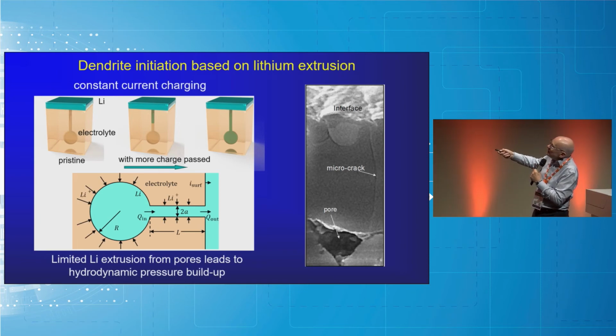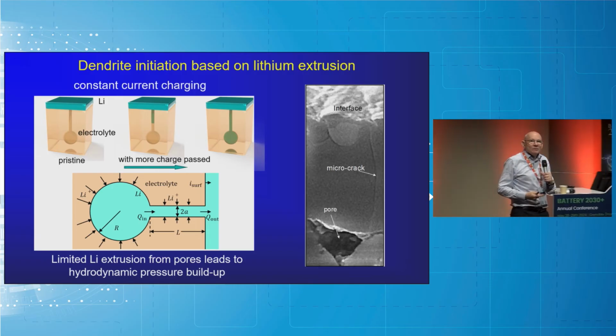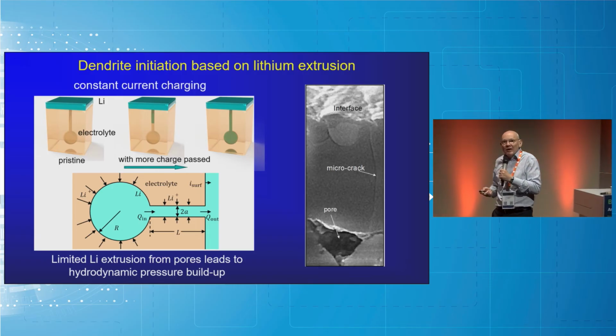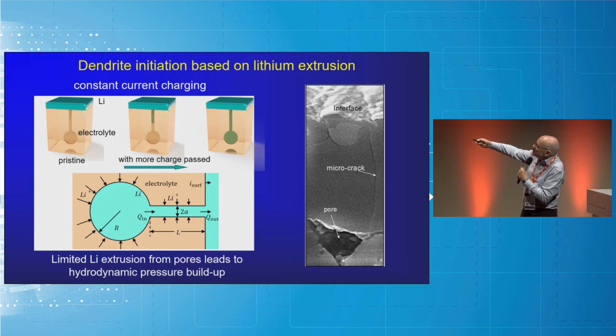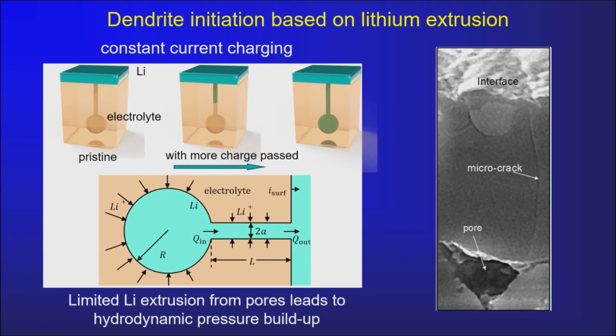You're going to be reducing lithium now across the whole of the surface of this pore because it's filled with lithium, so it's got a source of electrons. So you're reducing lithium ions from the solid electrolyte, and lithium atoms are trying to force their way into this space here. Now, lithium is a viscoplastic material. In other words, the model is basically one of hydrodynamic flow. There's this buildup of lithium here, and it's trying to release it by forcing lithium along the narrow crack. So it's an extrusion process, a bit like squeezing a tube of toothpaste. It's hard because you have a narrow neck and you're trying to squeeze a viscoplastic material through it.